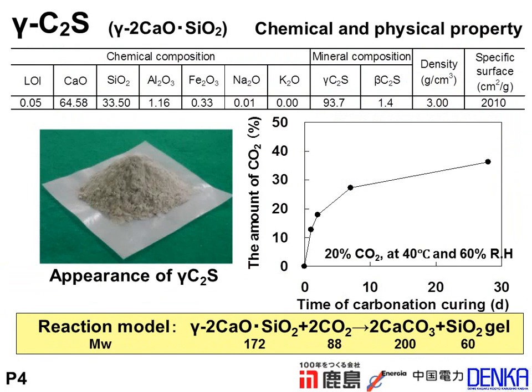The right figure shows the changes in the amount of carbon dioxide during the time of carbonation curing. The condition is 20% carbon dioxide, 40 degrees Celsius, 60% relative humidity. So you can see that the amount of carbon dioxide in gamma C2S increased according to the time of carbonation curing. It reached around 40% after 28 days. So gamma C2S reacts with carbon dioxide and generates calcium carbonate and silicon dioxide gel.